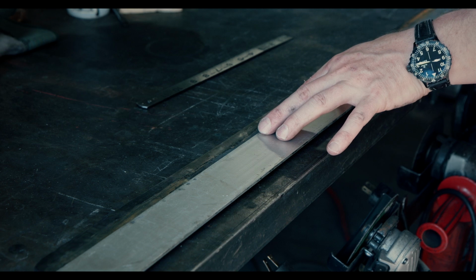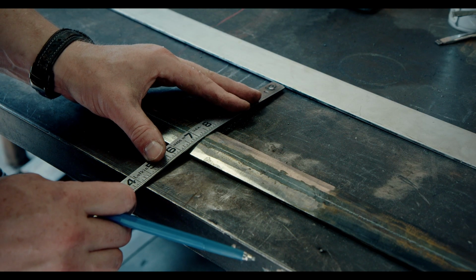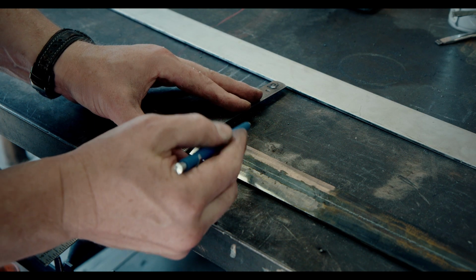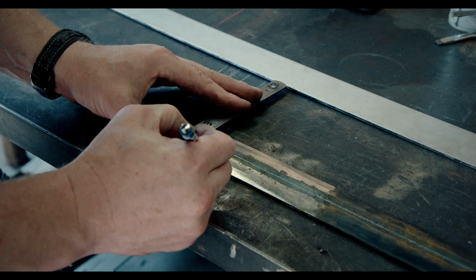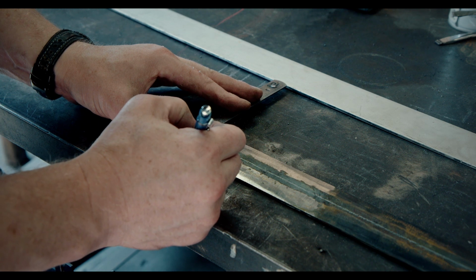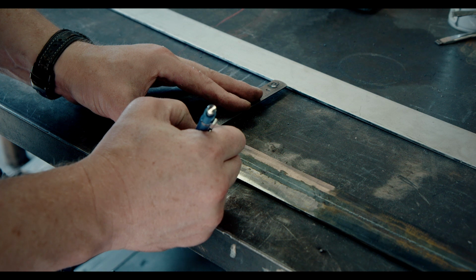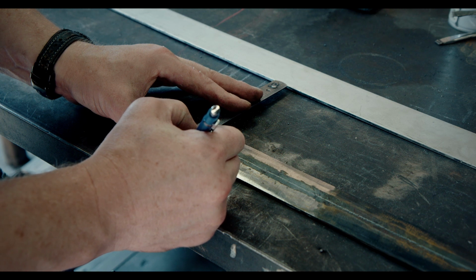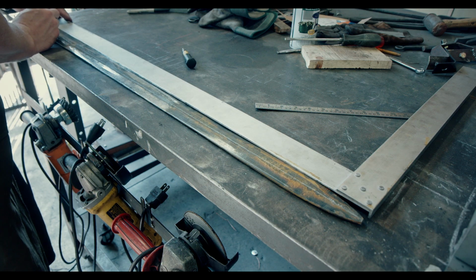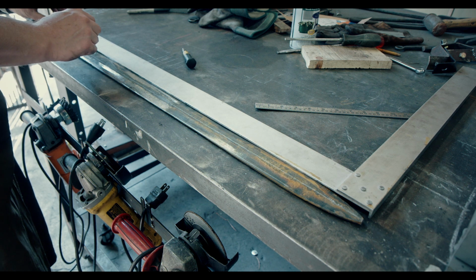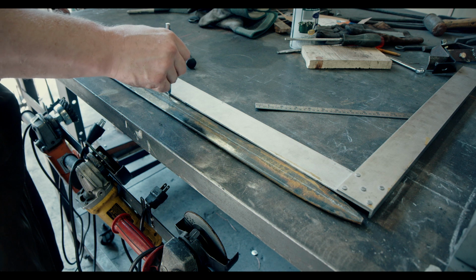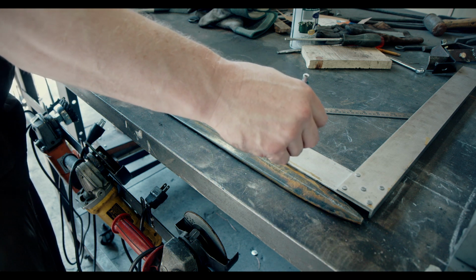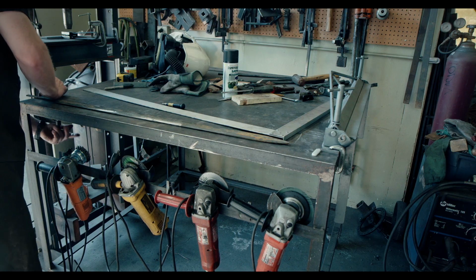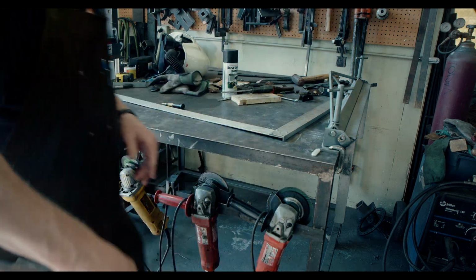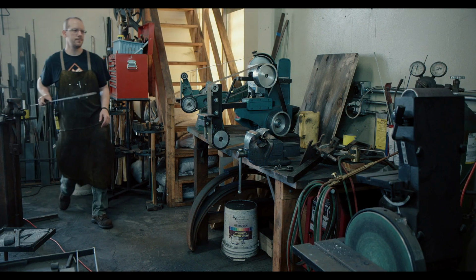Heat treating is the process in which the edge of the sword is hardened so that it can hold a sharp edge. With a sword as long as this one, symmetry becomes very important. You might ask why, so let me try to explain to you. While I am by no means an expert in metallography, I can tell you that a minimum amount of carbon is required to allow the hardening of steel. Steel starts to be hardenable over 0.35% of carbon, but for swords I usually work from anywhere above 0.6% to about 1%.